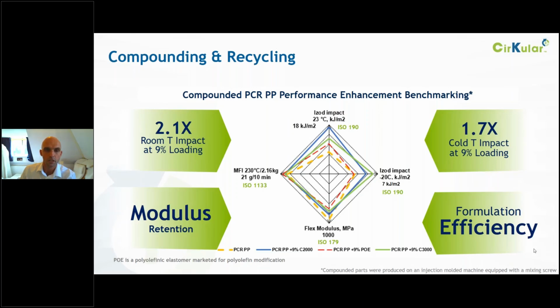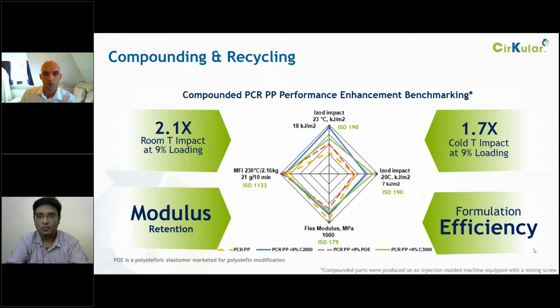There's a much stronger balance between the modulus that you want to retain, because you don't want weak objects, you don't want things to bend too easily, and the impact improvement that you can reach. This chart is showing in yellow the PCR polypropylene. I believe this was a 95 or maybe 98% pure one, so it's already a fairly pure one. But you see that the impact resistance at room temperature, and especially at low temperature, is not good enough. Now, adding about 9% of the Circular Plus additives increases that impact resistance, but keeps the modulus at a fairly good level. There's also a little bit of impact on the melt flow rate.